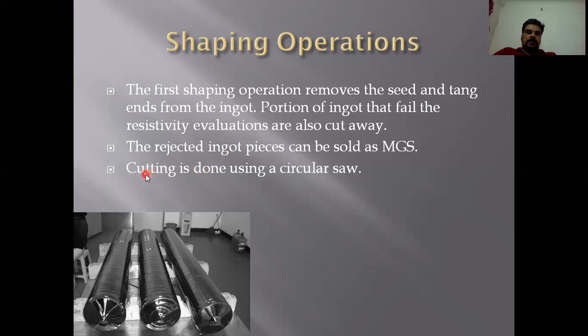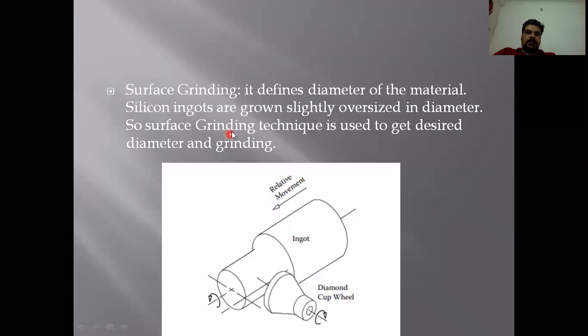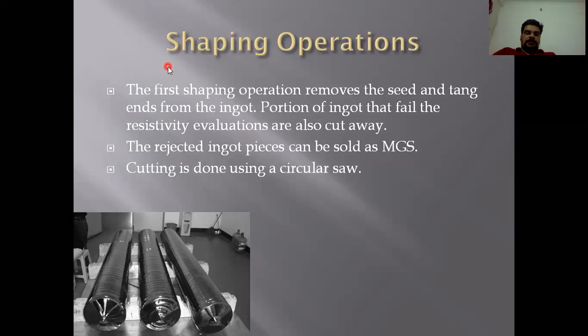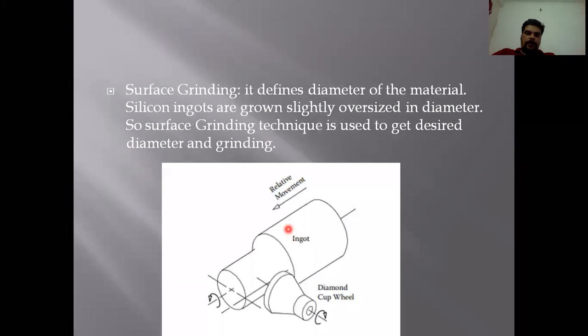Now cutting is done using a circular saw. We use a circular saw in order to cut the seed and tang ends. Now after this step, you can see that there are certain irregularities on the surface of the ingot. In order to remove these irregularities, we use the surface grinding method. This is the next step in silicon shaping.